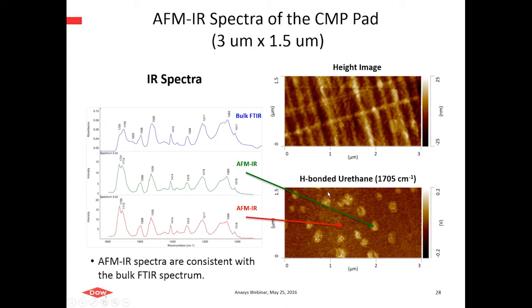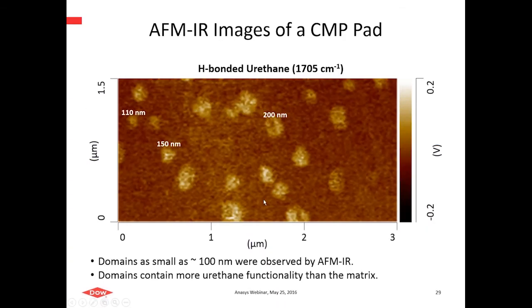And if we go after something like urethane chemistry, where we look at hydrogen-bonded urethane at 1700 wave numbers or so, and scan over this cross-section, we now bring up these harder segments, harder domains are starting to light up in this morphology. We can see that, not with as good a signal to noise as we've seen before, but clearly you can identify their locations. And this is now a blow-up of that image, just to convince you that some of the domains we see are approaching 100 nanometers, and we are able to resolve them.